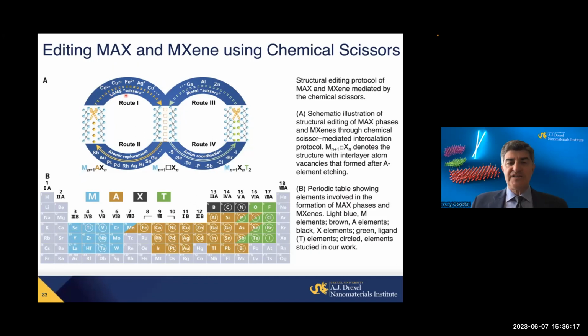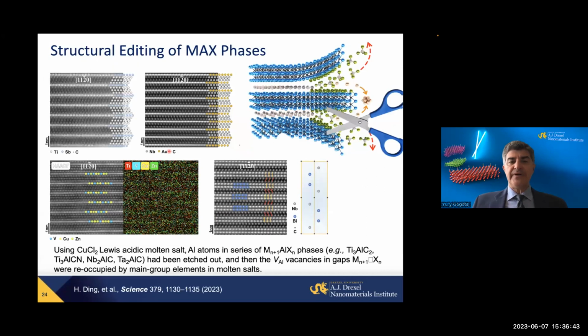And we can get different elements between the layers of MAX phase, removing elements, making vacancies, substituting the elements. And also we can make MXene with a variety of surface terminations. Again, halogens, but also phosphorus, antimony, halogens, chalcogens. So basically further expanding the range. So we take MAX phases, the layered structure I showed to you, put them into molten salt, etch away one element, get inside another element. Actually, even noble metal, you can get gold inside of niobium carbide between the layers, or antimony.